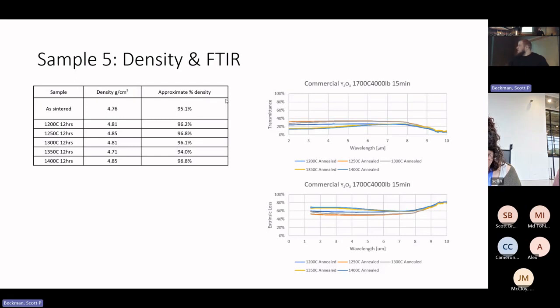So that tells us that I believe there's an issue with the transmittance measurement. When you're using the FTIR sample holder, you have to mask parts of it off, and because our samples are irregularly shaped, it's not always possible to perfectly cut off the edges. So sometimes, even though what you have is more optically transparent than you'd expect, when you measure it, because it's an irregular shape, you might be cutting off one of the highly transparent areas. In the future, when we rerun more experiments, we won't be subdividing our pellets to the same degree, so we'll be able to look through only the center of the pellet, which has the lowest carbon content. So it'll give us a better idea of what we're looking at.